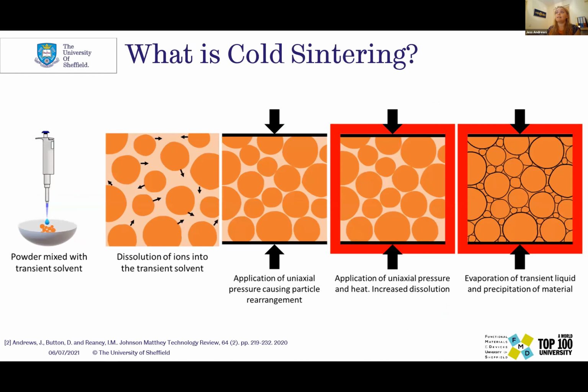Cold sintering seems a fairly simple process. There's lots of science that goes behind it, but eventually you end up mixing a transient solvent with your powder, and that encourages dissolution into that solvent. You then apply a uniaxial pressure and heat your whole system, and that allows the liquid to evaporate again and hopefully leaves you with a nice dense ceramic that's got some useful properties. Sometimes you need to do some heat treatment afterwards to retain the properties that you want. But there's some really interesting science being done to get super dense bodies once you've just done something at around 200 degrees. So Dan's going to talk to you about some of the work he's done on zinc oxide.